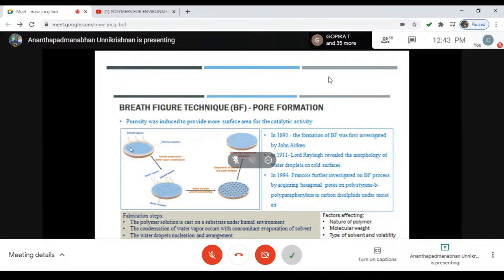What you do is you take polylactic acid and silver particles dissolved or dispersed in a solvent like chloromethane. Obviously, when you expose it, the solvent will try to vaporize. But if you do this process in a humid chamber where a lot of humidity is there, there's a magic happening. As the solvent goes out, water will start condensing onto the membrane. You will see water getting condensed onto the membrane.